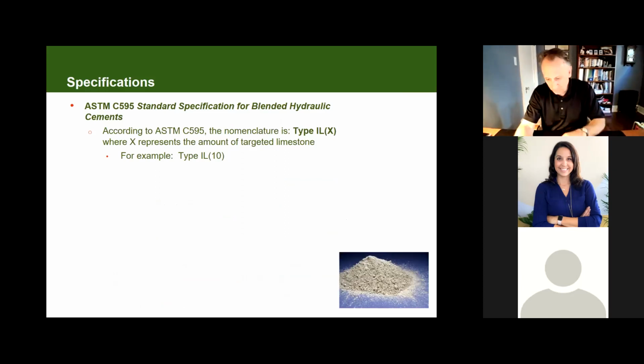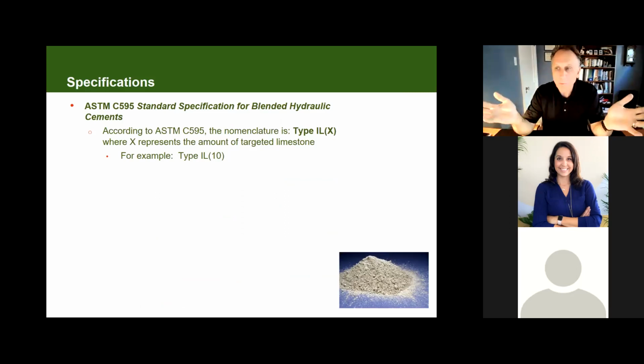So when you look at C595, you're going to see some nomenclature changes, right? So forever we've been using a type 1 Portland cement, if you will. Well, according to ASTM C595, the nomenclature is now going to be type IL, and then some parentheses, and you're going to have a value in there. Right now, I've got X there, where the X represents the amount of the targeted limestone. For example, a type IL10. So this would be a type IL limestone cement that has no more than 10% ground limestone in that 1 ton of Portland cement. Okay, makes sense?